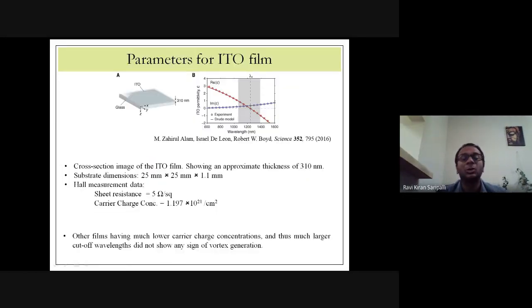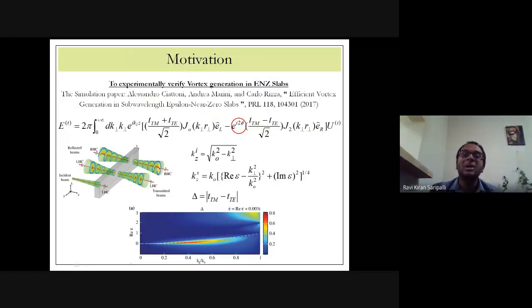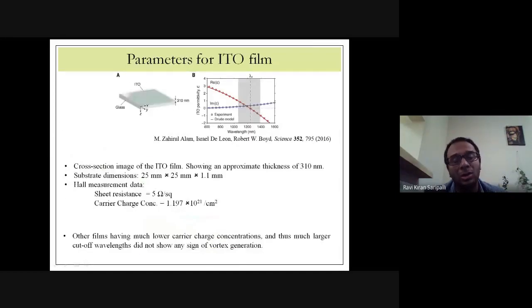So for this work, two things are important. One is selection of the film, and also being able to generate this wavelength in the lab. The film that we used is an ITO, or indium tin oxide film, and the carrier charge concentration was about 10^21 per cubic centimeter, and the thickness is 310 nanometers. So you don't really need precise nanofabrication facilities. You just need to deposit films either by sputtering, RF sputtering, or laser ablation, and you're able to generate these kinds of films. Of course, you need to manage the efficiency such that you attain large carrier charge concentration.